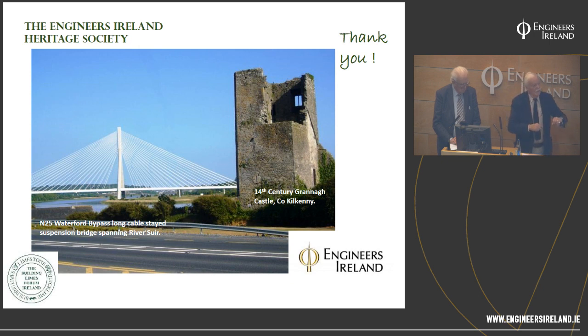With a free lime or a non-hydraulic lime or a quicklime mix not engaged with an NHL, you depend on the gods. It's the weather. And so the carbonation can take a long time. And this can be a problem. And so that's one of the disadvantages. And that's why most of them were mildly hydraulic. They weren't hydraulic to get a compressive strength, they're hydraulic to get a decent set, to have a mortar that was set to a degree that you could go away and leave it alone and let the carbonation continue.